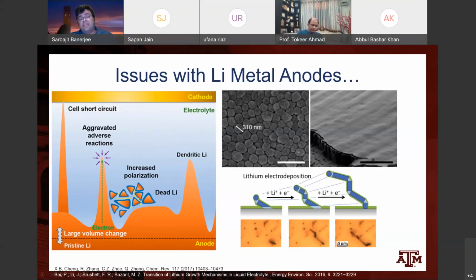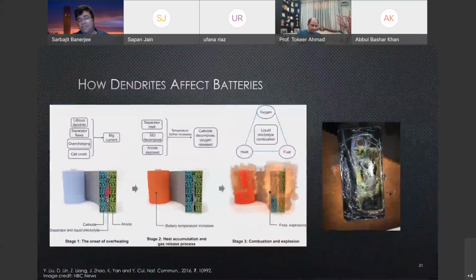But oftentimes instead you've got the formation and cracking and the reformation of the SEI, and ultimately pieces of lithium get covered with the SEI and either fall off or form a dead layer on top of the electrode that's dead lithium. And then of course again at these tips that are growing, the dendrite tips, because of the sharpness of the tip, you can have very strong electric fields, and those electric fields at these bare tips can result in further electrolyte decomposition reactions that continue. And the overall result is as the surface gets fouled and you have these complex SEI layers form, increased polarization of the cell.